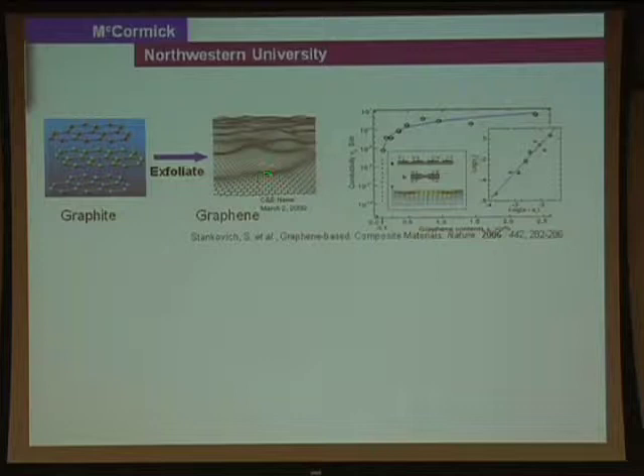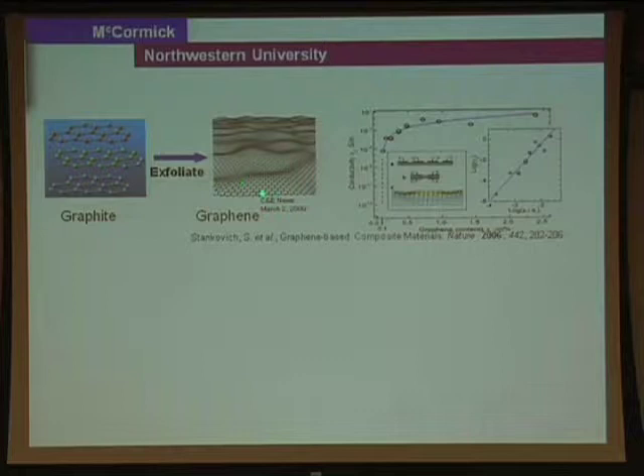The graphene layers are very special. They are very hard mechanically, and they are electrically very conducting. In fact, you can disperse this graphene material into a polymer, and that's done at Northwestern by the chemistry professors here. You can disperse it into a non-conducting polymer material and make that polymer conducting. As little as only 1% of this graphene can make that polystyrene quite conducting already.